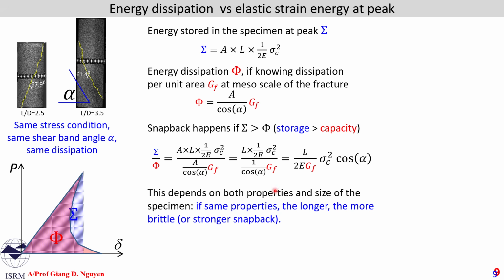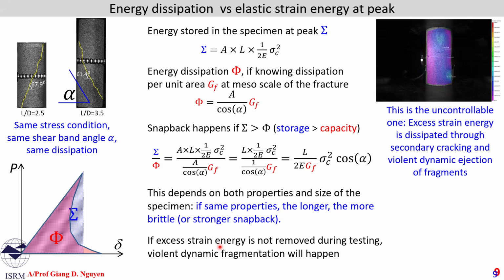So that means for the same materials, same properties, the longer the specimen, assuming the same cross-section area, the more brittle the load and displacement is, and hence more snapback is observed. This is what we have seen earlier in the previous slides. To control it, we need to remove the excess strain energy in the specimen so that the test machine can successfully capture this kind of snapback. If not, very brittle or violent dynamic behavior will happen, as you can see here from our test on direct vertical displacement control.